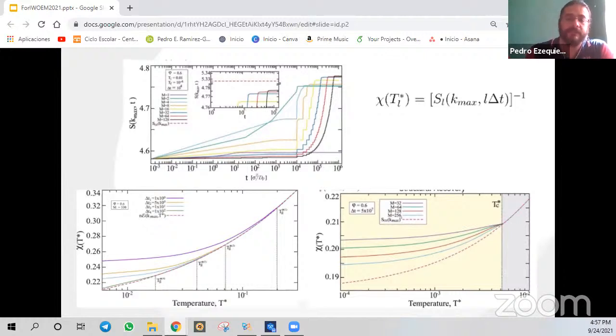We can present this information in another way. If we define chi of t as the response function associated with the inverse of the time-dependent structure factor, we can obtain the two plots at the bottom of the screen. In both, the dotted line is the equilibrium value of chi of t. The left plot presents results for fast cooling rates, and we observe that deviations from equilibrium start to appear above Tc. In contrast, on the right, we found that for slow cooling rates, the departure from equilibrium tends to Tc. In consequence, Tc separates the states which actually equilibrate from the ones which are not able to equilibrate.